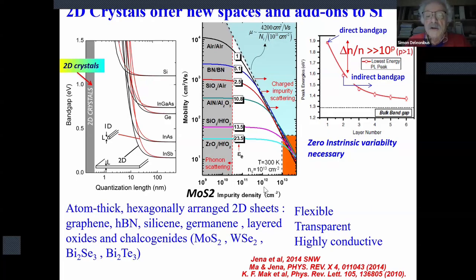Whether you have one monolayer here or 2 monolayers stacked on each other, you have different materials, direct band gap or indirect band gap. So zero intrinsic variability is necessary because you cannot allow to have one and a fraction of monolayer and a dispersion on a chip, for example, which wouldn't allow you to manage the number of carriers in a channel, basically the output current. So this is really an issue with this kind of materials. You need a zero intrinsic variability approach.